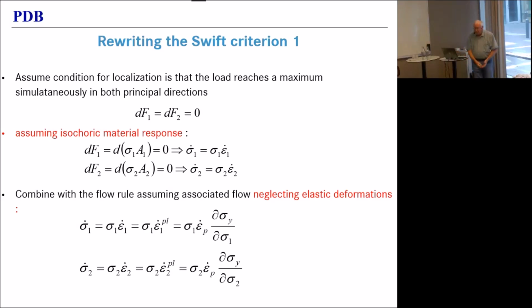Swift made a very simple assumption. I think nobody knows where it comes from. I don't think he knew. He just figured out that it somehow worked. He made the assumption that in the two directions, we simultaneously reach a force maximum. So we reach a state where dF1 and dF2 are simultaneously 0, which is a straightforward generalization of the Considère criterion. The only thing I can say is don't think about it too much, because the only thing you'll get from that is a headache. Believe me, I tried it.